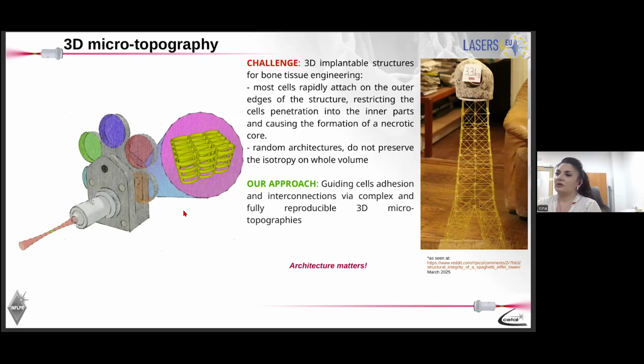Using this 3D lithography technique that I showed you at the beginning of my presentation, we fabricated microstructures having such an architecture that they are able to support the attachment and growth of osteoblast cells, which are very strong attaching cells and, as I showed you earlier on the slides, pull with very high forces on the substrate. So this time we want our structure to be very strong from the mechanical point of view, so that it supports the cell growth.